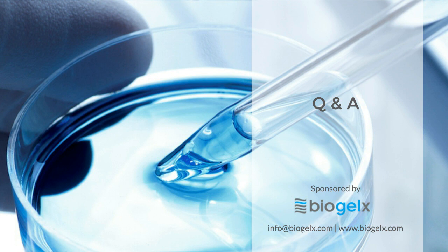It's Mitch here. I think I can take this question. So it isn't a necessity to use media to cause the gelation. You could use a calcium chloride solution if you wanted to. Effectively, what's causing the gelation is the divalent cation, and these materials are commonly found in most types of media. So it isn't specifically media; it's the divalent cations that are needed in order to cause the gelation process.